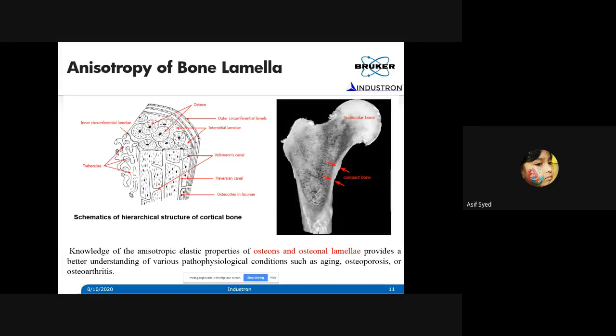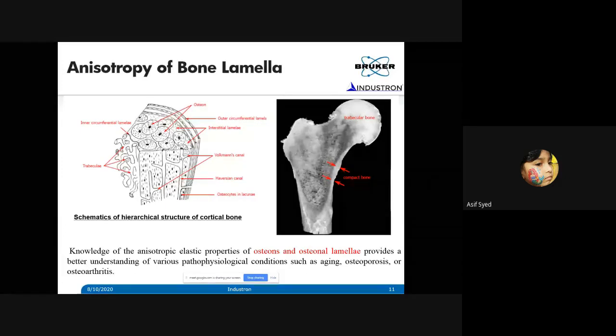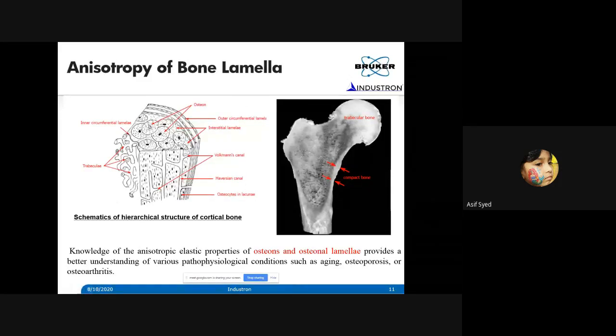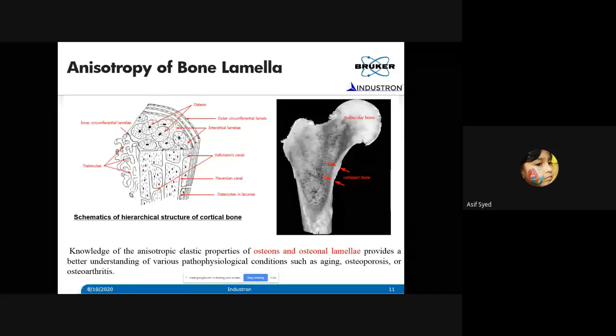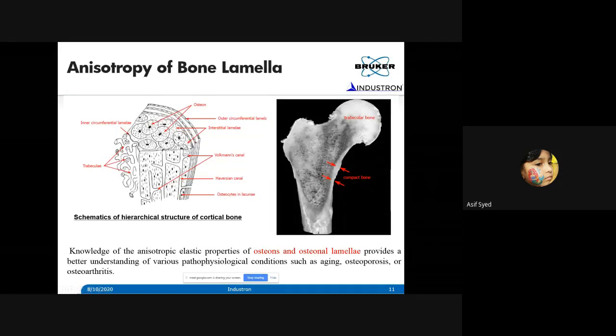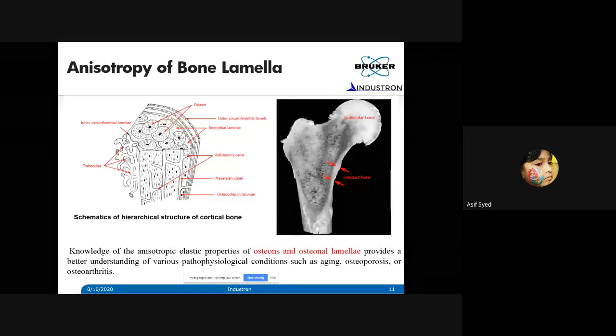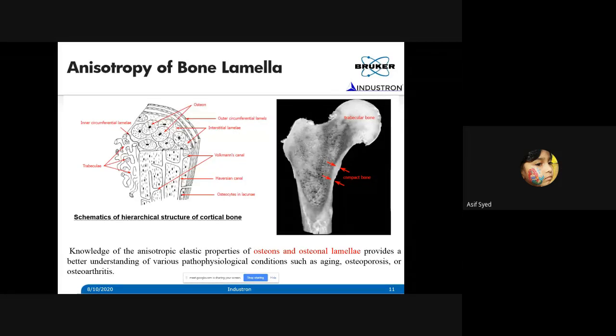Because now we have technology where we can go down to nanometer length scale, we can go down to this microstructure and understand those properties, right? So for example, these osteons have a tubular structure, and lamellas are basically layer on layer like onions, right? And depending upon the orientation of how you do the test, the properties may be different. That's why I call this slide the anisotropy of bone lamella, right?